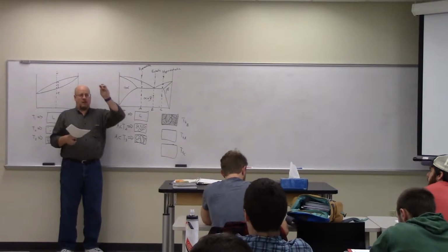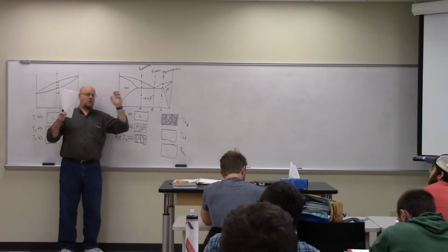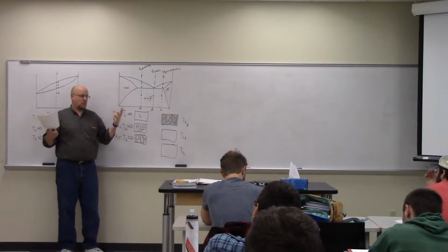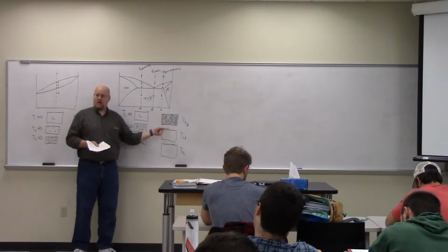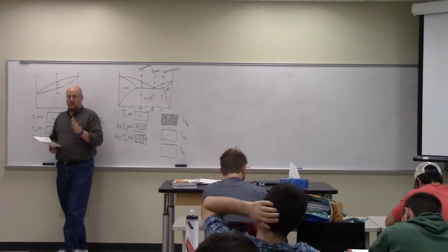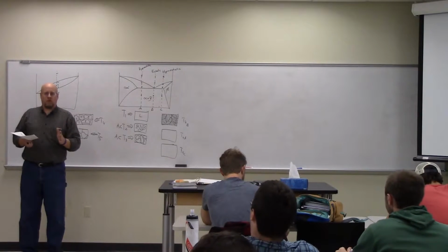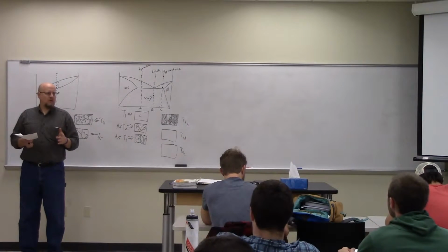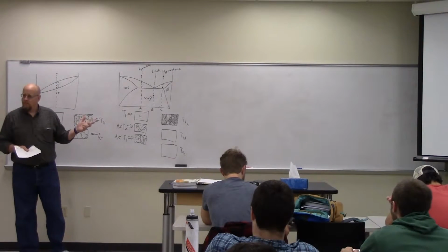You can have a big beta thing with nodules of alpha, or individual separate grains of alpha, and different structures depending on how you cool it. But in general, you're more likely to get a lamellar structure, and the layers will have thickness in proportion to the slowness of the cooling. So the thickness of the layer is inversely proportional to the cooling rate. That make sense?